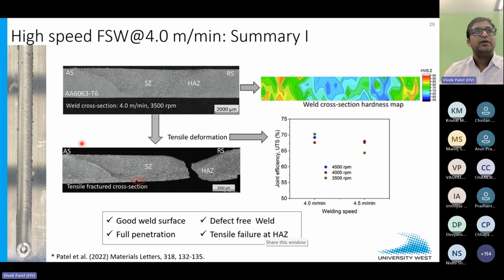You can see the parameters, and when we see the fractography after the tensile test, the weld failed from the heat affected zone. Initially, during the tensile testing, it tried to open from the root. You can see some void during the tensile testing, but ultimately it failed from the heat affected zone, having around 75% joint strength.